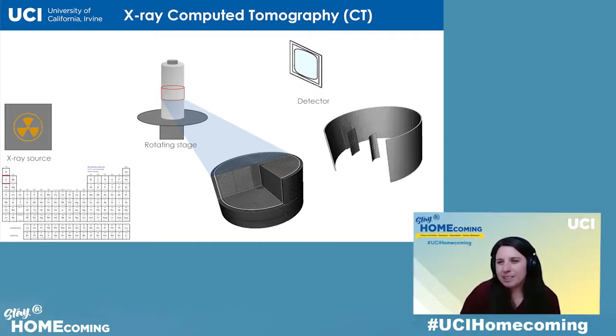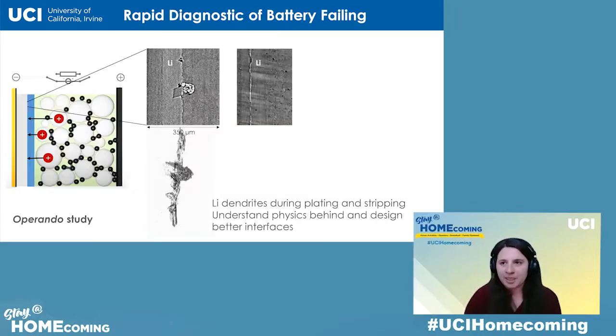Challenge with lithium imaging with X-rays is that lithium is a very light element, so it's not going to be detected by X-rays. But at UCI, we developed techniques to actually detect lithium with X-rays. At UCI, my group uses the technique as I described, X-ray computer tomography, to probe dendrites in actual real cells.